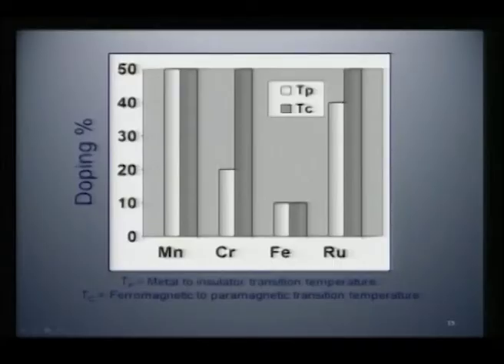Suppose it is only manganese, then the manganese 3 plus, manganese 4 plus concentration is like this, and therefore you can see a very strong double exchange mechanism in manganese. But if you substitute chromium in the site of manganese, you can see that the metal insulator transition is happening up to 20%, although the ferromagnetic transition is still there up to 50%. This is a very strange thing, that you can see ferromagnetism equally strong up to 50% of chromium, whereas the metal insulator transition deviates.